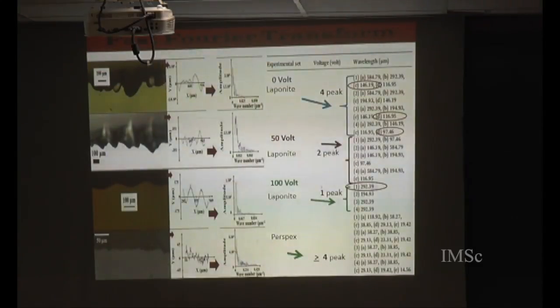And this was done for a number of specimens for these 3 cases. This is the original outline, one of the crack contours. It was transformed using ImageJ to this outline, and then the Fourier transform is here. It looks small, but I think you can make out that there are a number of peaks. And each of these 4 different cases are shown for each of these voltages. And these are the wavelengths which are obtained. This is for the 50 volt, this is for 100 volt, and this is for the Perspex sheet.